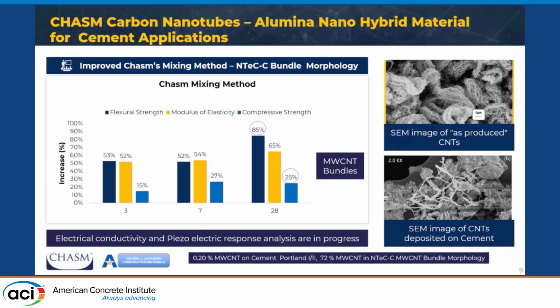There are some estimates that if the flexural properties increase by around 70%, we can potentially reduce the pavement thickness by about 25 to 30%. That means that we can cover more surface area with the same amount of material, which has an impact on the cost. We can observe SEM images of the material as produced, and after incorporating or depositing these individual bundles on the cement particles.